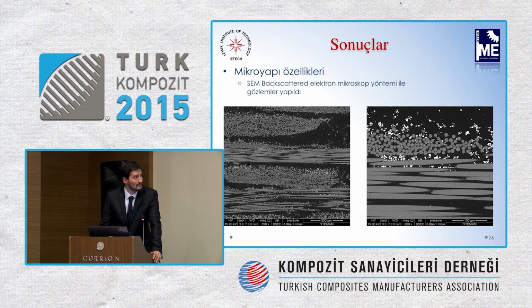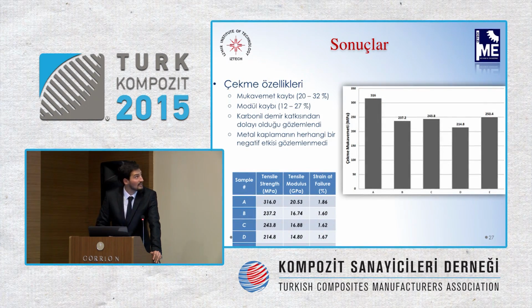Microstructure, SEM graphics. The backscattering electron method is used, and it creates contrast differences based on the atomic number. And of course, the atomic number of iron is high. Therefore, carbonyl iron can be detected within the structure as white dots, and glass fiber can be seen easily. And there are 0 to 90 direction glass fibers here. Here, carbonyl iron is not distributed in a homogeneous fashion, and that has an impact on our results.